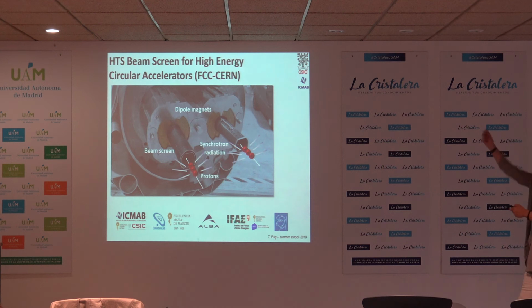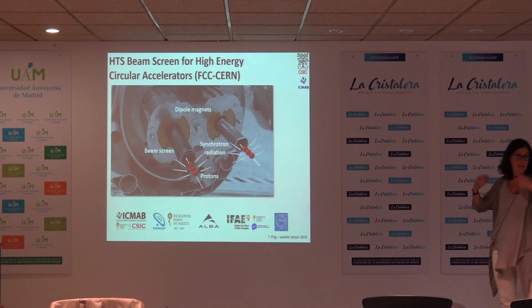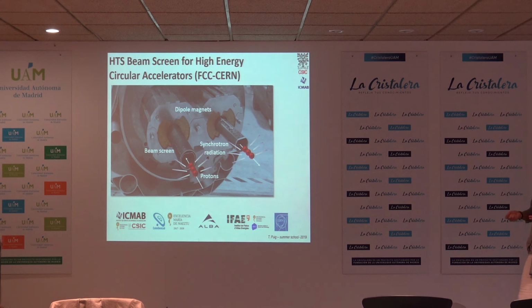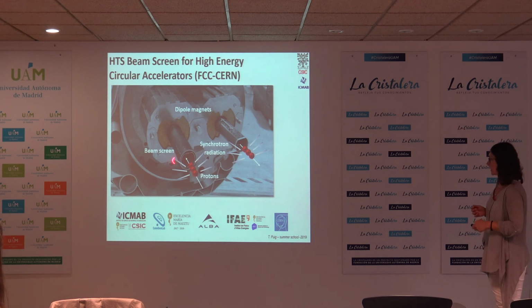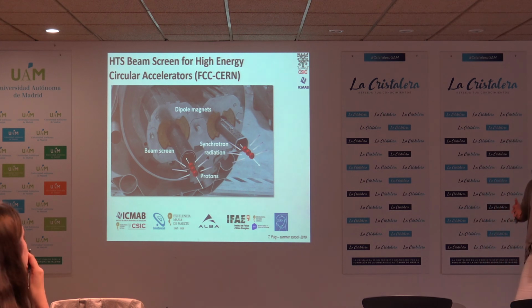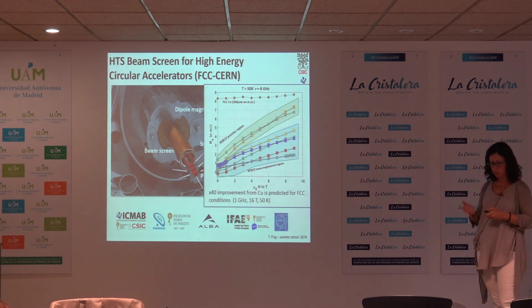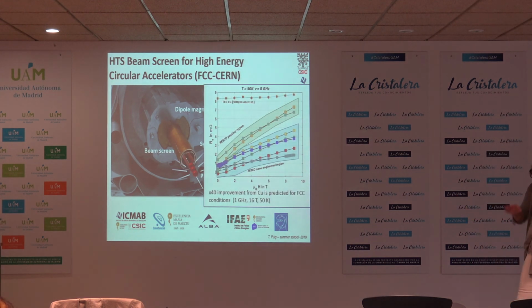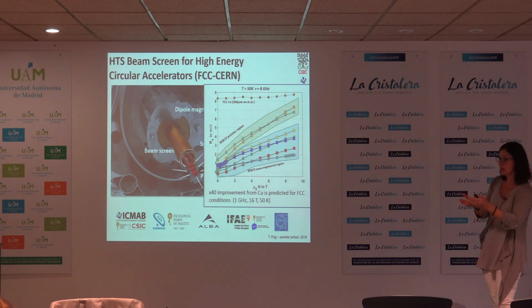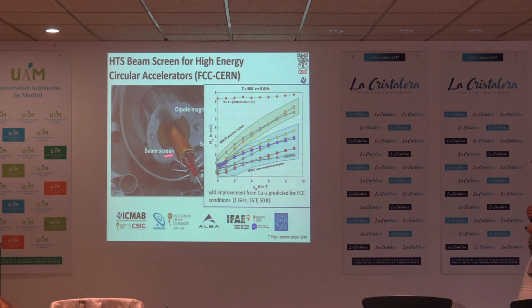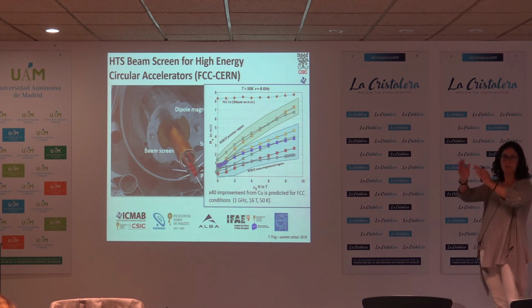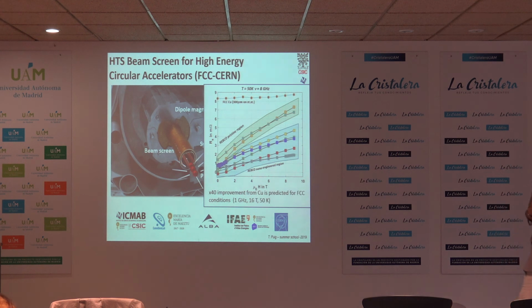However, the problem is that when you go to FCC, the energy associated to the synchrotron radiation, because the energy of the beam will be so high, is so huge that they cannot just cover this beam screen with copper in order to ensure that there will be no fluctuation of the magnetic field. And here is why we propose that in that case we could use a superconductor, a high-TC superconductor, a cuprate conductor, which would cover the interior of this beam screen, and that would ensure that the surface resistance inside would be low enough so that all the charged particles would not be influenced by the fluctuation of the magnetic field due to the synchrotron radiation.